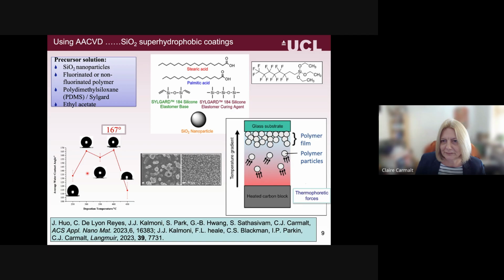But we did a similar mixture where we had the silica nanoparticles. Again, we used different scales, so very small and some larger ones. Then we added in either a fluorinated silane, or to move away from fluorine, because obviously that has some environmental concerns, we also have looked at using a mixture of stearic acid and palmitic acid, because these fatty acids also provide the sort of low surface energy that's required.